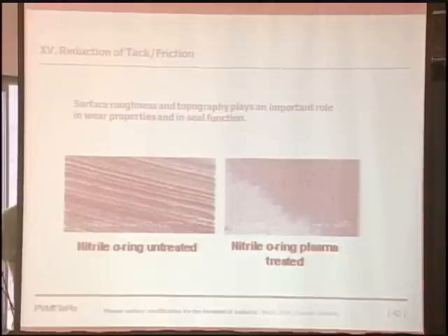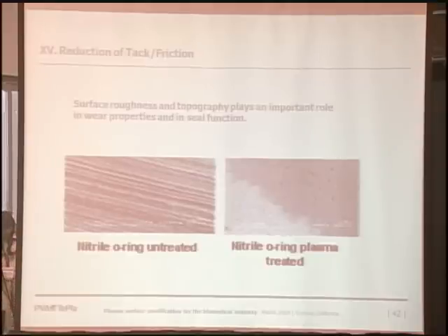So we did some extended plasma processes to see what the etching rate was, because when we saw this, we thought we were actually etching the material. It turns out we weren't. So we're hypothesizing as to how plasma works. What we think is happening is plasma is breaking and activating these long chains at the edges or sharp corners. They're kind of folding down and reabsorbing to the surface is what we think is happening.